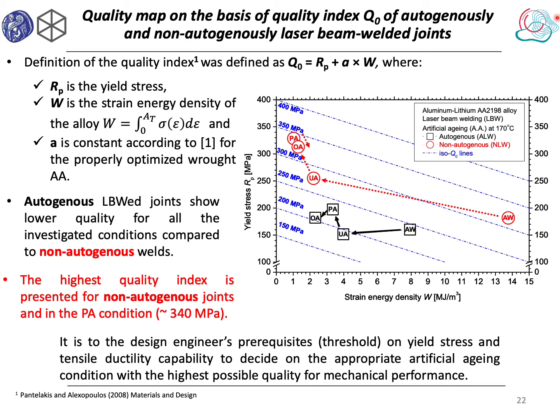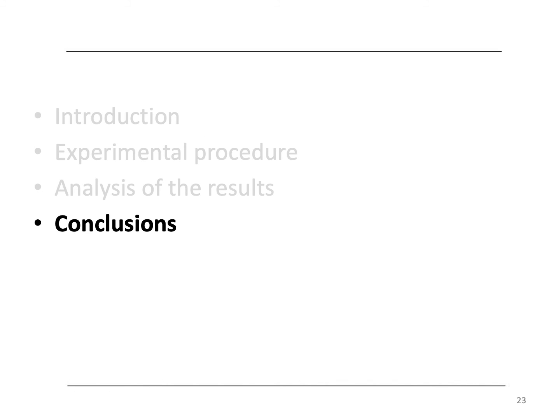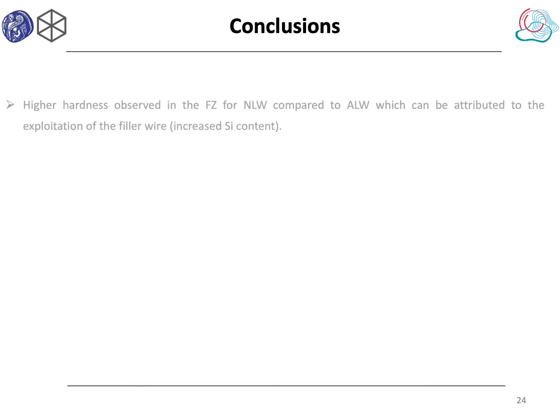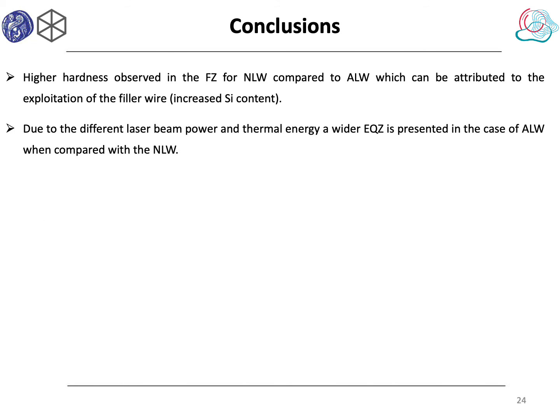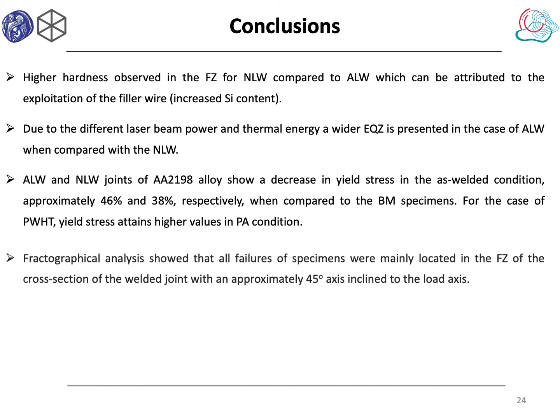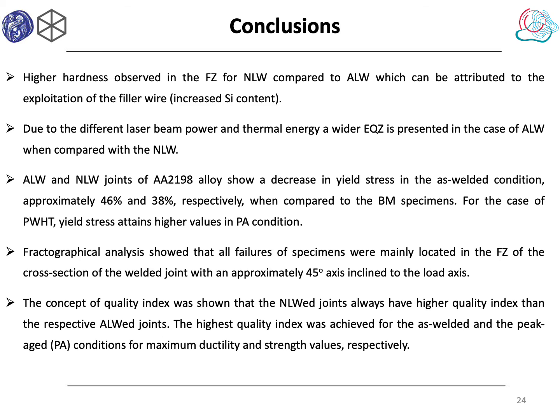It is up to the design engineer's prerequisites on yield stress and tensile ductility capability to decide on the appropriate artificial aging condition with the highest possible quality for mechanical performance. To conclude, higher hardness was observed in the fusion zone for non-autogenous welds compared to the autogenous, which can be attributed to the exploitation of the filler wire.